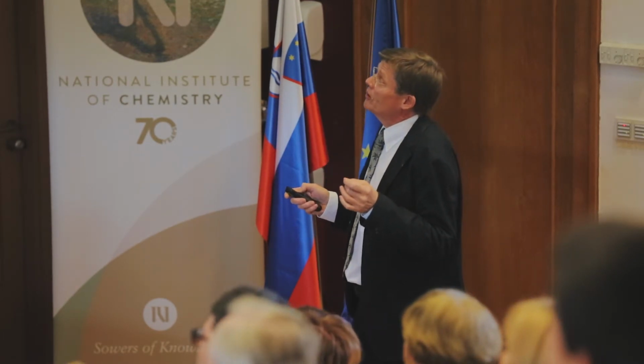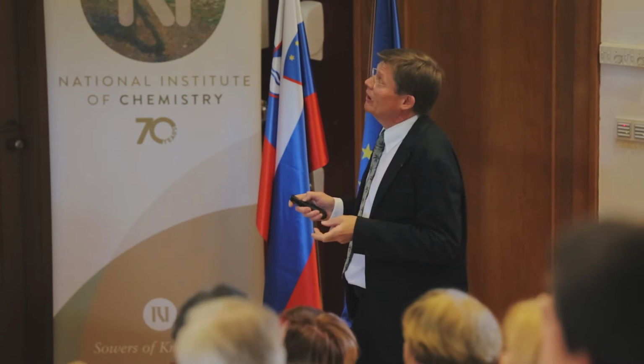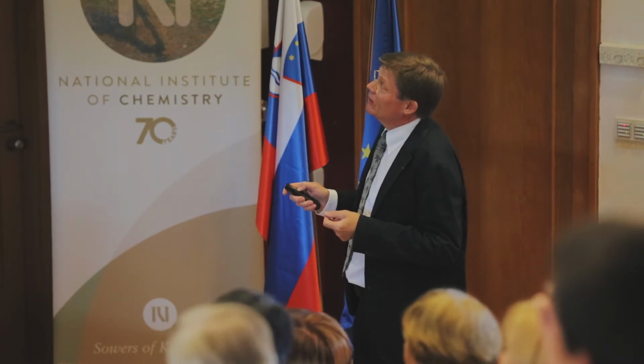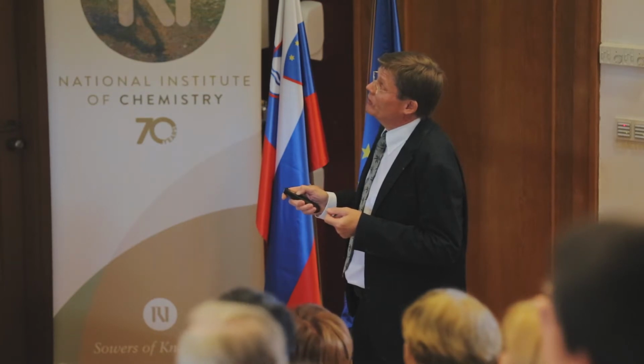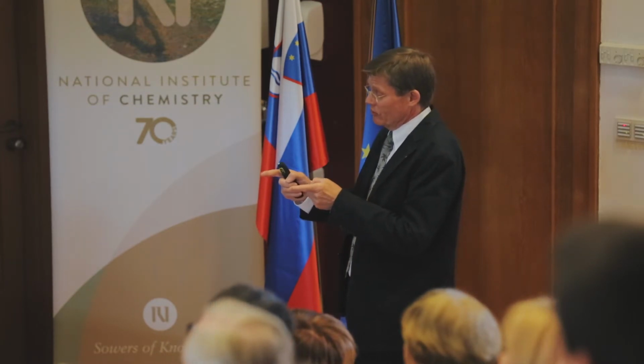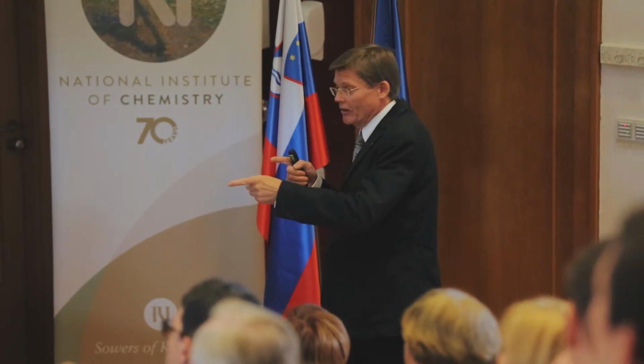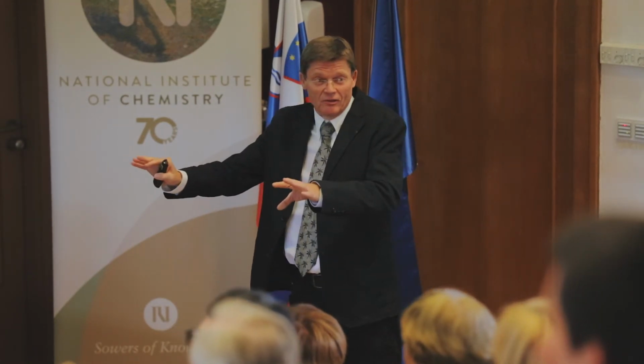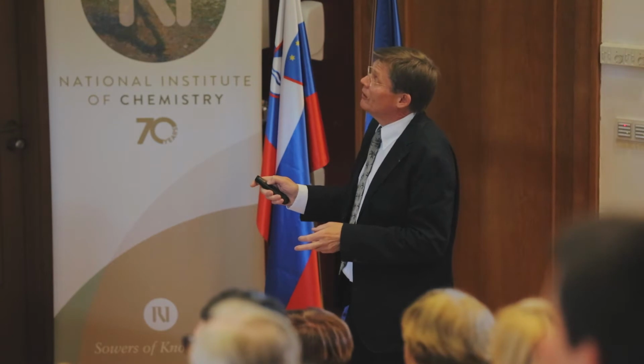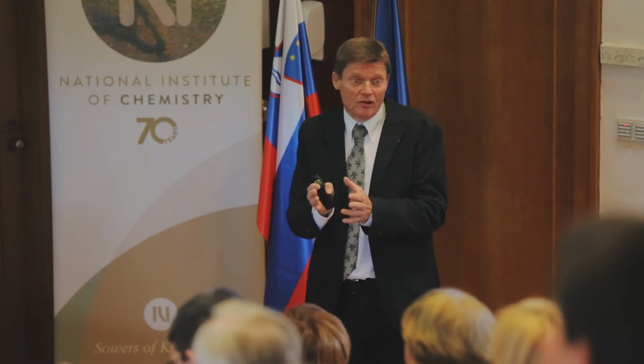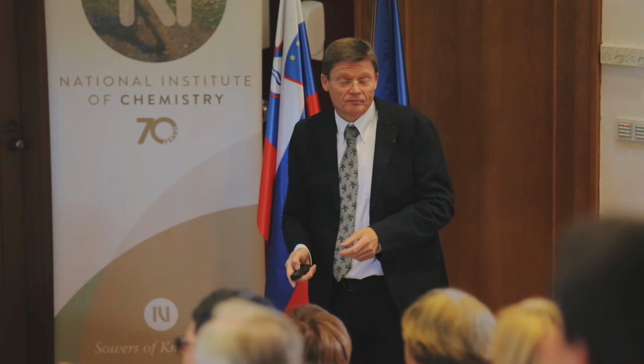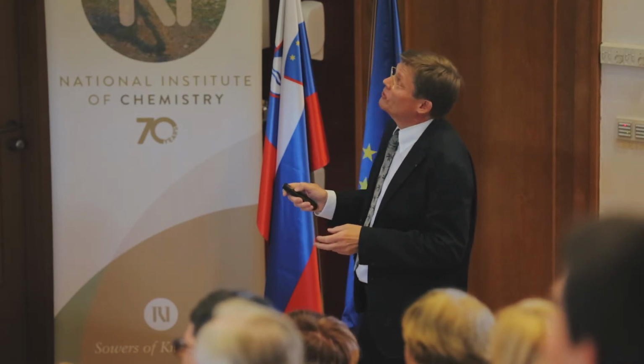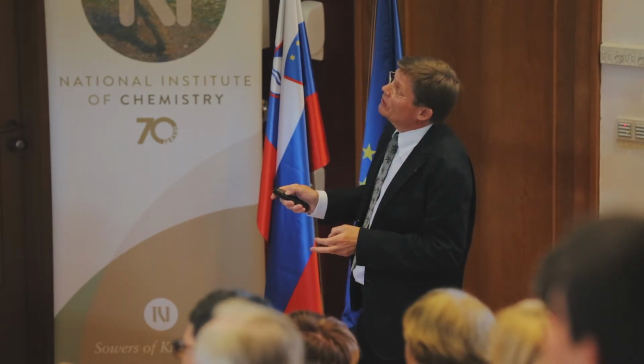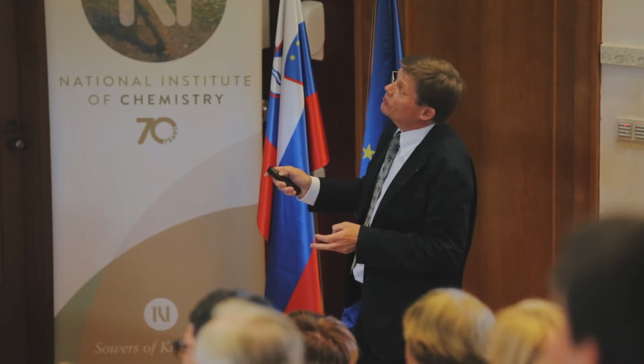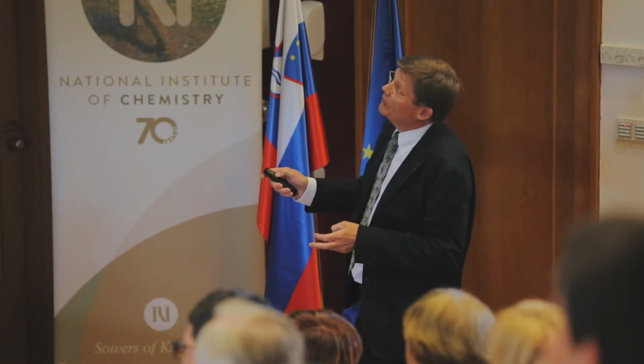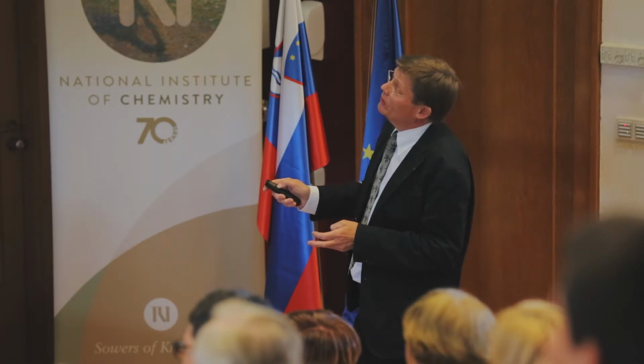And this again has to do with the chemical capacitance and chemical resistance. The chemical resistance is given by ionic and electronic conductivities, and now the ions go the silver iodide way and the electrons go the graphite way. They share it. And the capacitance is good because you have space charge effects in addition to the normal ones. So this is a picture of how silver goes into the composite. You can have a diffusional path directly here, but you can also charge it from the material.